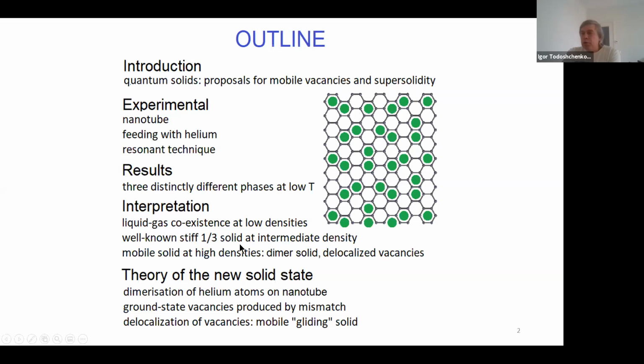The interpretation we give to this phenomenon is that we form dimer solids: solid made of bosonic dimers, which contain a finite amount of vacancies even at low temperatures due to the mismatch between the carbon lattice and the helium lattice.